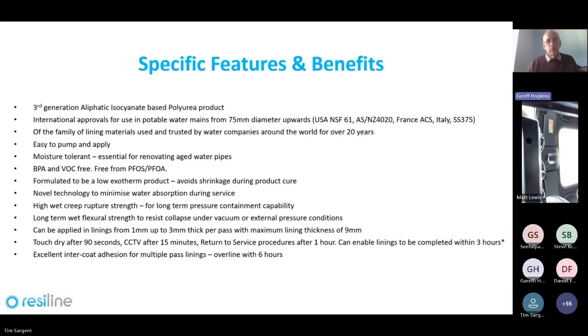Consequently, we have a high wet creep rupture strength, which is what you need for long-term pressure containment ability. And we have a high long-term wet flexural strength, which is what you need to resist collapse under vacuum or external pressure conditions. In the UK, we can apply our material from 1 millimetre up to 3 millimetres thickness per lining pass, with a maximum lining thickness on our Reg 31 of 9 millimetres. The product is touch dry after about 90 seconds. You can CCTV and review your lining after 15 minutes, and you can commence return to service, which is generally spray chlorination, after 1 hour.